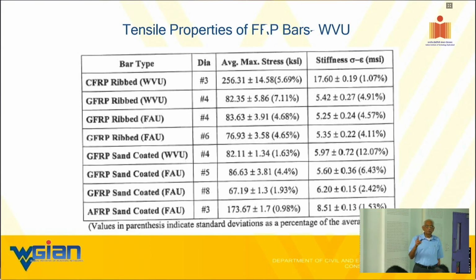Instead, I would much prefer to talk about it from the strain point of view. But the problem with the strain point of view is that I gave you the 20,000 number based on 60% volume. If it is 40% volume, the strain number goes up. You see, so there are issues like that. Therefore, computationally, stiffness computation accuracy is superior to strength computation accuracy.